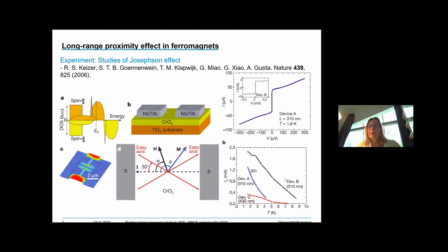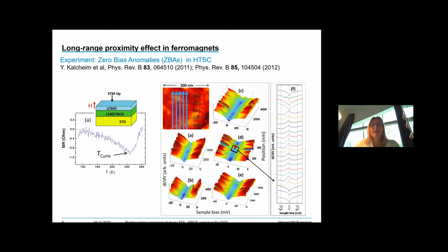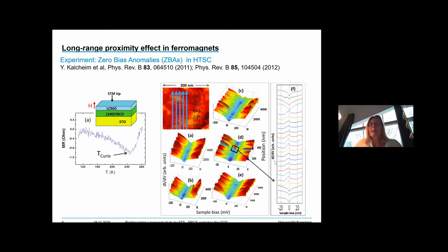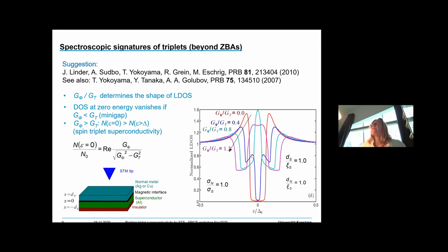One can have a Josephson effect over a junction of two superconductors and a ferromagnetic insulator half-metal, requiring some non-collinear magnetization components for the supercurrent to survive over long distances — hundreds of nanometers, not just a few nanometers as in the short-range ferromagnetic-superconductor case. One example of a zero-bias anomaly comes from the Jerusalem group, on YBCO and magnetic material LCMO, probed with an STM tip from the magnetic side.